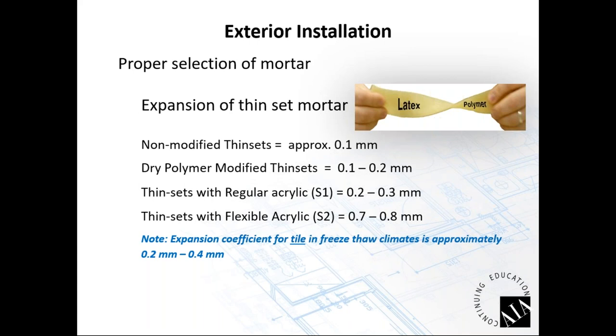Then we get into your mortars that are mixed with liquid acrylics or liquid polymers. A regular acrylic, we're starting to see movement of 0.2 to 0.3 millimeters. And we get into your advanced flexible acrylics, 0.7 to 0.8 millimeter movement. So what this is saying is that by using these two-part polymer modified mortars with a very flexible acrylic, the mortar has more capability of moving than the substrate or the tile or stone that you're bonding to. So it becomes kind of like the elastic in your sock. If you keep stretching the elastic in your sock, if it isn't a good sock, the elastic breaks down and your socks don't stay up. A good elastic, socks last. Same type of thing. These good polymer modified mortars for an exterior application will last the lifetime of the building, the life cycle of the building that you're expecting out of it.